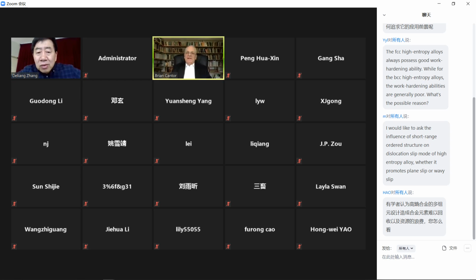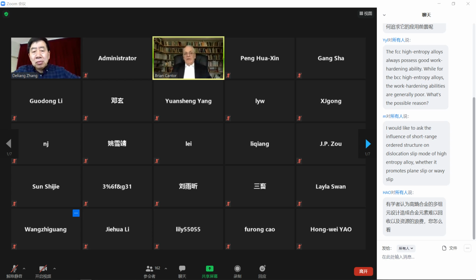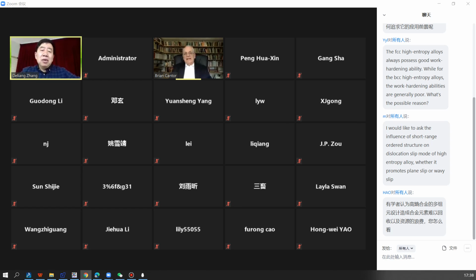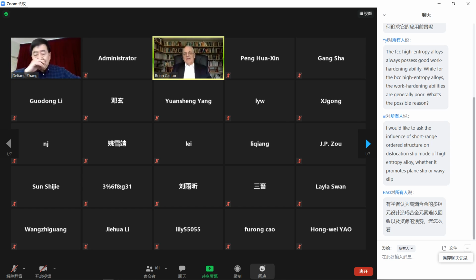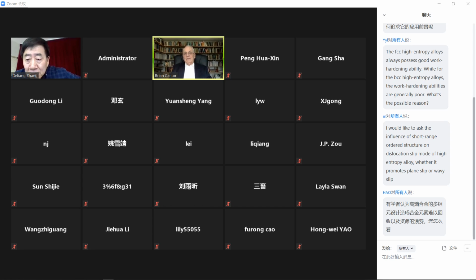Yeah, well, it's the same as in pure materials. In pure components, the work hardening of BCC is less good than FCC. But the basic reason is exactly the same. You don't have enough slip systems. You have fewer slip systems in BCC than in FCC because in FCC they're sliding on 111 planes, as opposed to 110 planes. That's the basic reason, but the details are very complex, and people are looking into it. By the way, work hardening isn't the most important thing because the BCC Cantor alloys have got fantastically high yield strengths.